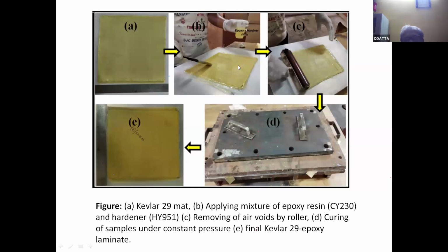It's a simple technique, and when we apply the brush, some bubbles may be there in the liquid. That bubble is to be taken out, and that's why a rolling action is very important, because if you have a bubble inside, it will act as a void when the laminate is cured. That is not desirable; it will remain inside the laminate as a flaw. No one wants a flaw. After that, this is put in some device. There are molds, so we put them and let them cure for say 24 hours.